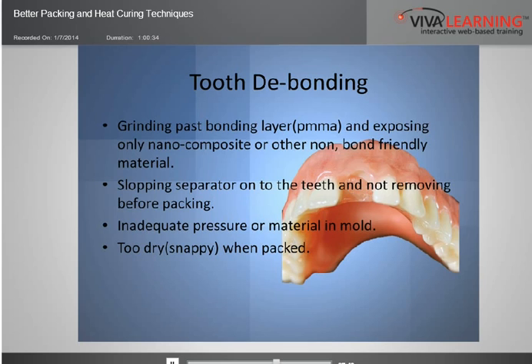Also, you got to be careful with that separator. If you slop it all over the backs of those teeth, and you don't remove it before packing, and I mean remove it with either monomer or some sort of bonding liquid, you're setting yourself up for eventual failure. You see this picture, you've seen these. Clean as a whistle here, and just the neck where it's underneath the acrylic, it snaps clean, but this is all clean, it never bonds, and that's that material. Or it could be the separator. Also, again, I'm going to go back to this inadequate pressure or material in the mold.